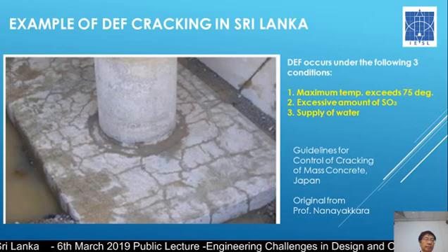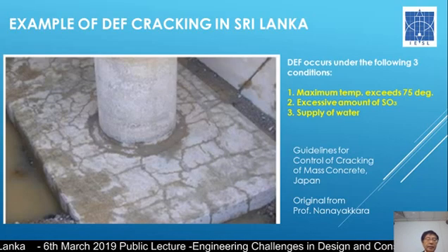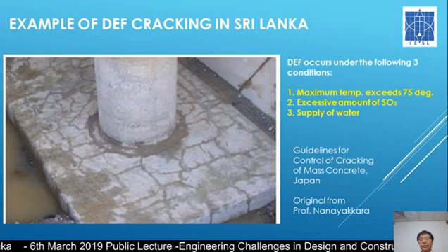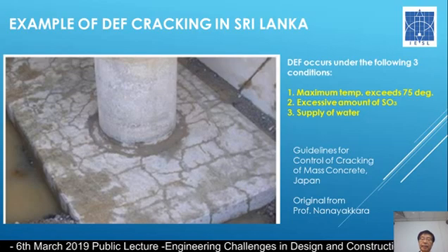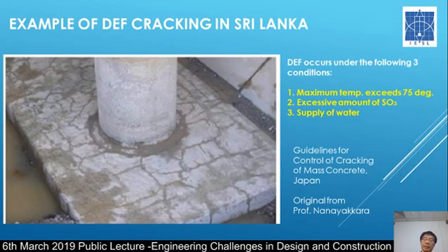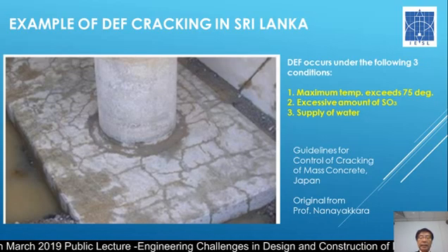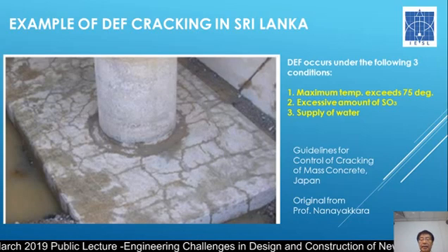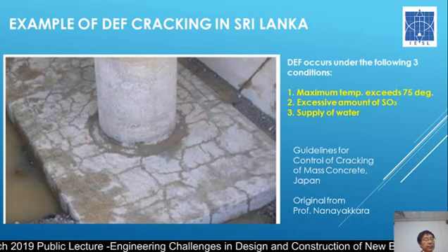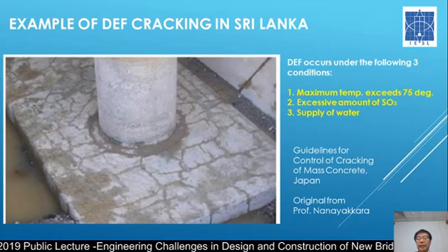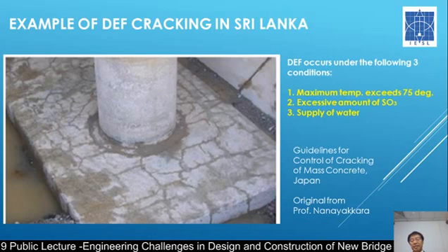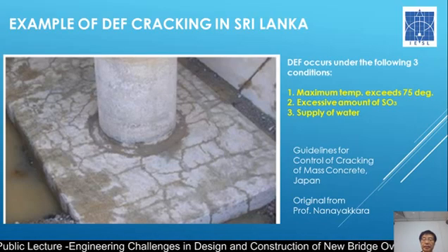The lesson we have learned is that DEF is still not fully understood, but the maximum temperature should be limited to some degree, in this case 75. And also the cement has to be reduced in SO3 or C3A. But this is very difficult.